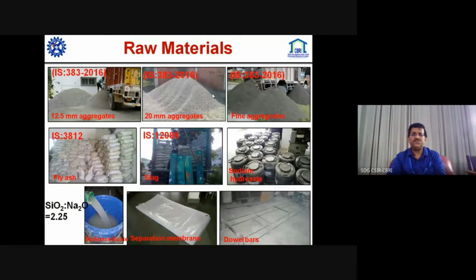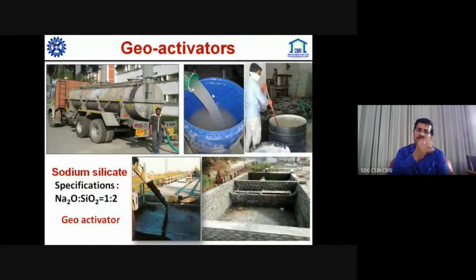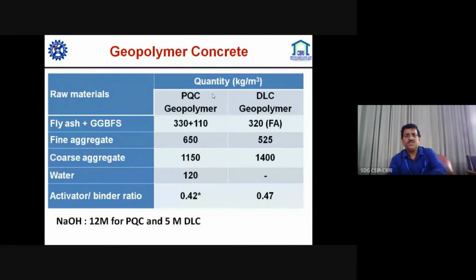If you look at that, the same material has been used, only that in place of cement we are using fly ash, ground granulated blast furnace slag, and alkali activators, that is nothing but sodium silicate and sodium hydroxide. Other properties we have done with mix proportions. This is sodium silicate, you can see, and sodium hydroxide flakes, and we make the activator. So these are the raw mix proportions.